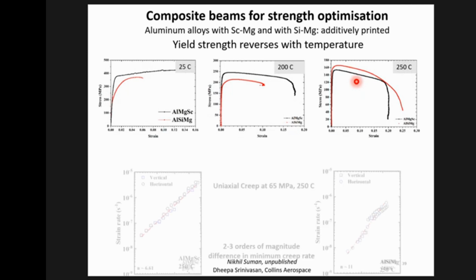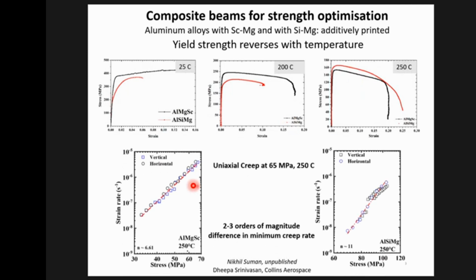And if you look at the creep behavior at 250, you will find that the aluminum scandium magnesium alloy creeps about 100 times faster. Notice that the stresses here are 30 to 70, whereas in the case of aluminum silicon magnesium, it is 60 to 100. So if you look at comparable stress levels, you're looking at a ratio of about anywhere from 50 to about a few hundred. So now the question is, is there a way of making a sandwich whereby you retain your room temperature strength, but also don't pay the penalty when you go to high temperatures?